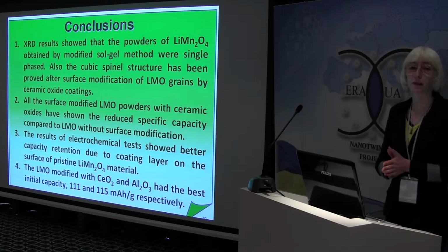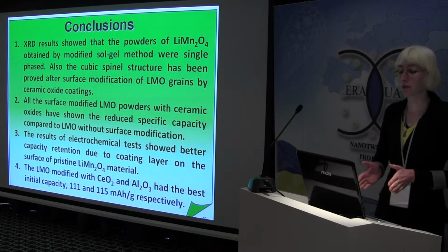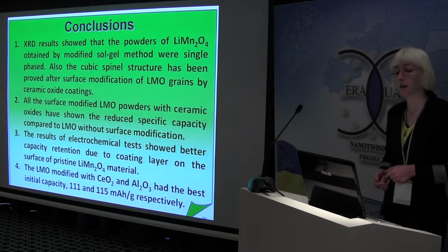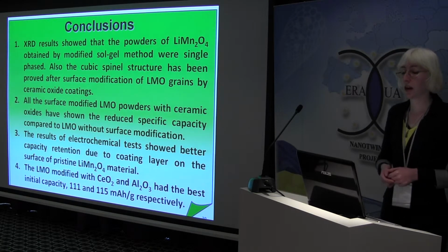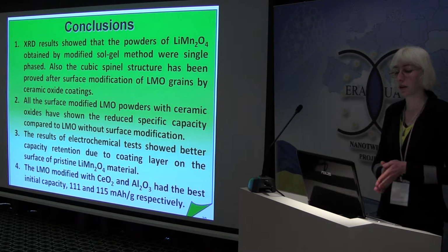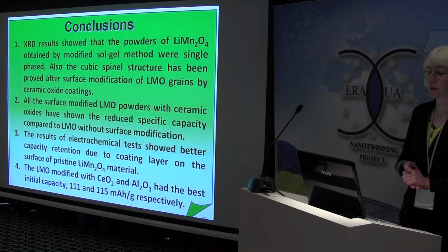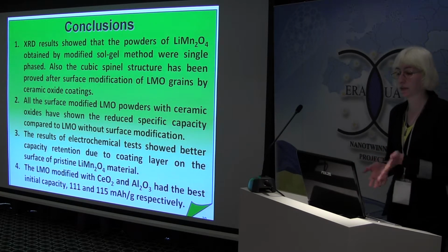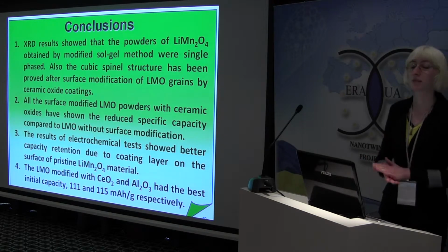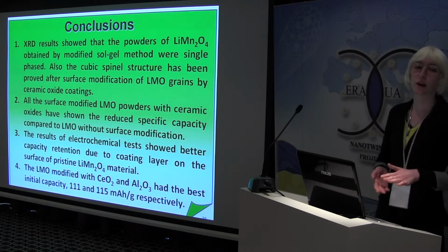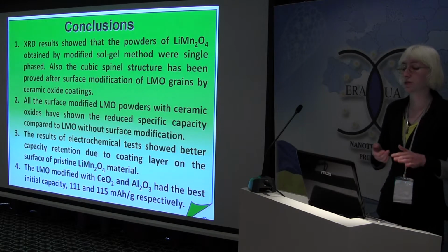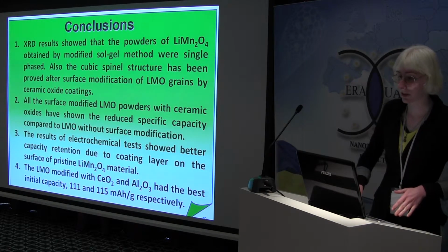The results of electrochemical tests show better capacity retention due to the coated layer on the surface of pristine lithium manganese oxide powder, and the best result for initial capacity we obtain when we modified lithium manganese oxide with cerium dioxide and aluminium oxide.